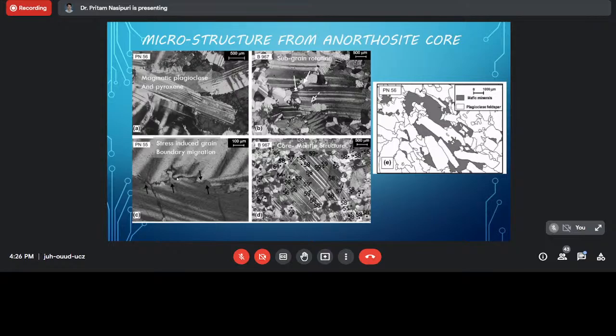Now, finally, this is a picture which shows the mafic minerals and plagioclase. Most of the plagioclase in the undeformed part preserves the magmatic texture, but where the grain-to-grain boundary between these two feldspar grains is achieved, a variety of microstructures occur, ranging from subgrain rotation, strain-induced grain boundary migration, and core-mantle microstructure. And all these features are indicative of dislocation creep accommodated deformation.